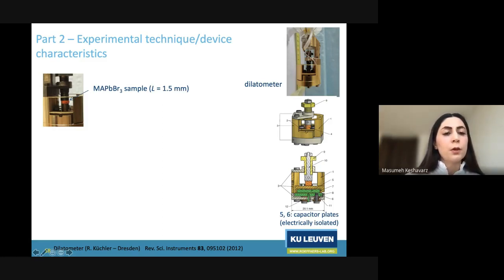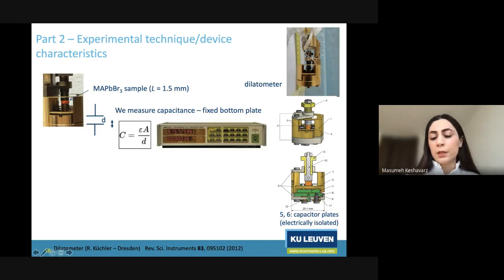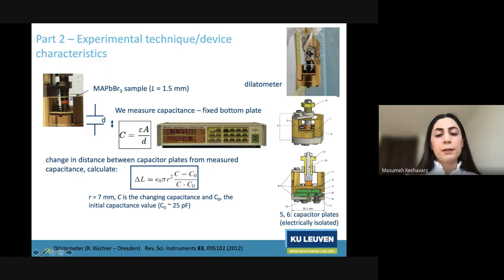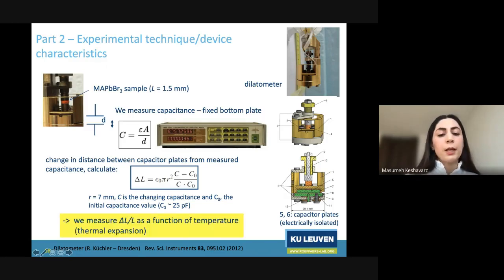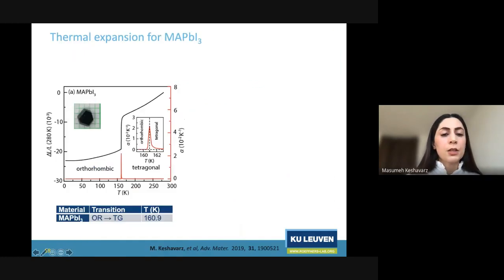You mount your crystal between two copper plates, and on the figure at the bottom right you can better see how the capacitance is measured, between these two plates. Any change in one axis of the crystal, which can be A, B, or C, gives a linear thermal expansion that can be measured through the capacitance. The capacitance is measured through a bridge, and then the length is calculated using this formula. What we see later in the plots is delta L over L. Delta L is the change in the length along one axis of the crystal, mainly the C-axis in this study, and L is the room temperature length of the crystal, so the changes are normalized to the room temperature length.